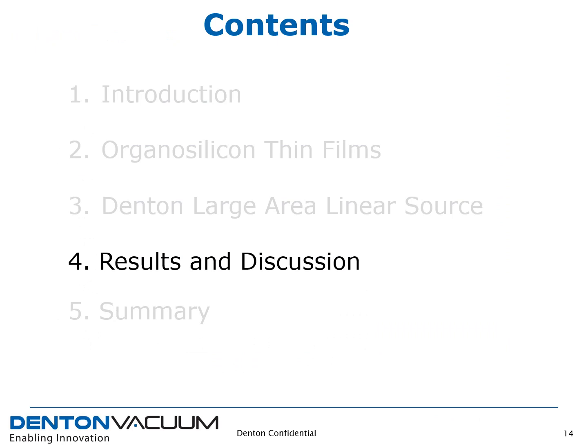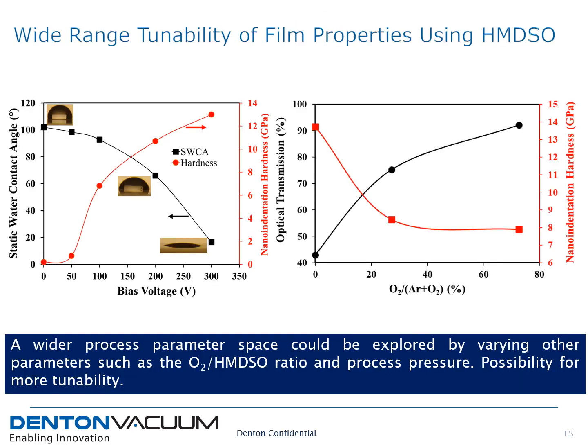So now we'll go into some of the results that we have obtained recently. All these coatings were done using HMDSO, argon, and oxygen. So what we show here is that a wide range of tunability of film properties can be obtained by varying the process conditions. For example, what we see here is the static water contact angle and the nano indentation hardness plotted as a function of the bias voltage, the pulse DC bias voltage that increases the ion energy.